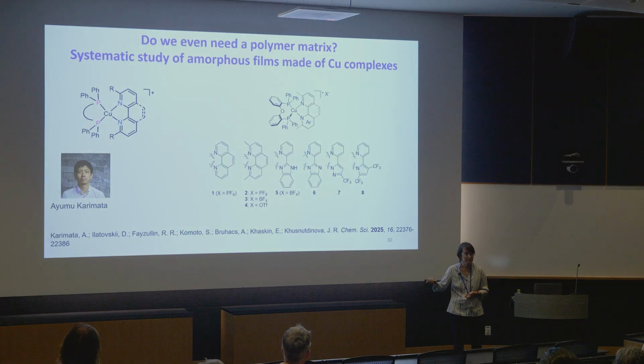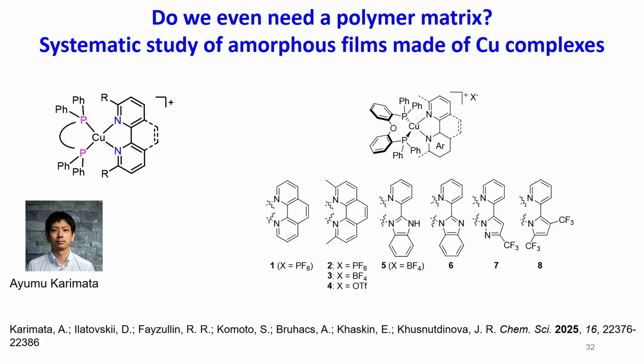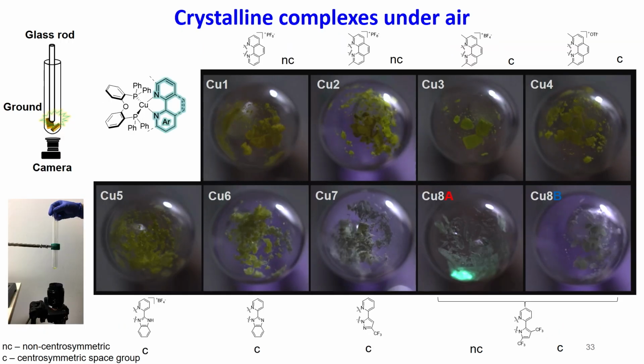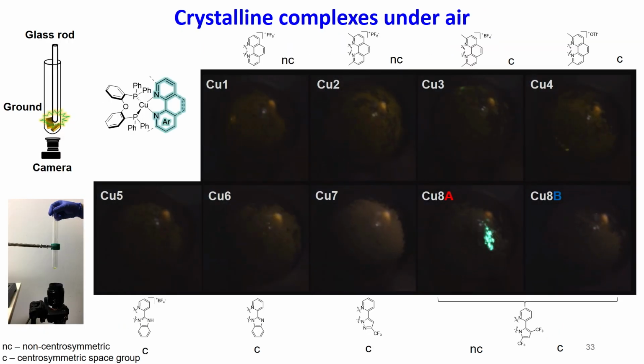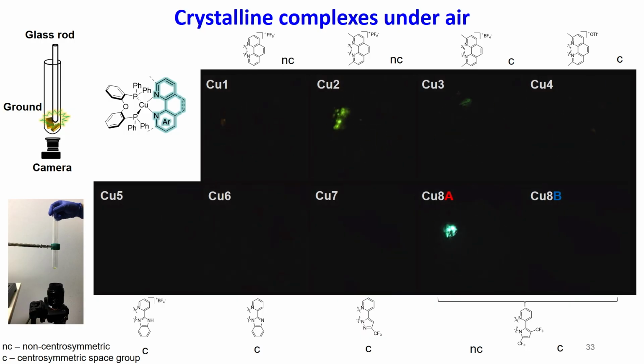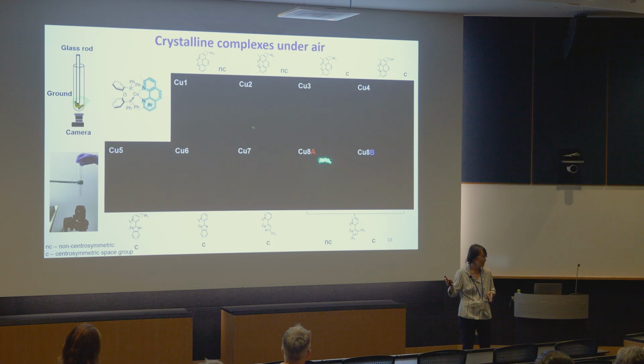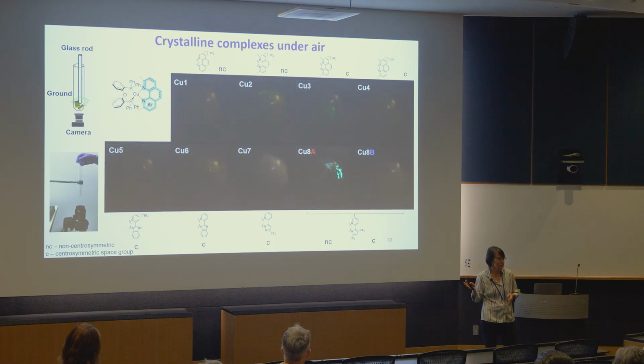And Ayumu in my group initiated this study of looking at a series of copper complexes. And one question we wanted to elucidate is, what's the relationship between triboluminescence in a crystal phase and in amorphous phase? So we found that if you look at the crystal samples of the series of complexes, some of them are triboluminescent and some of them are not. This is not unexpected. This very much depends on the crystal structure. It's difficult to predict. You may find some trends, but not a very clear trend.